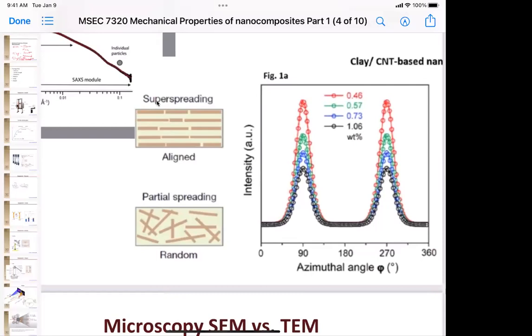And then by flipping it over, what we see here is if we have this randomly displaced thing, we're going to get a slightly higher signal, but it's not going to have these big peaks in it. Once you have this at the 90 degrees and 180 from the 90 to 270, you'll get the intensity of having those spacings you're seeing, the order you're seeing. Remember that order is on that 2 nanometer thickness scale. It's the plates that are all aligning, and that's what gives us our big scattering peaks that we see.